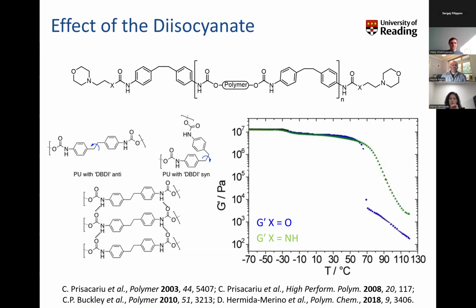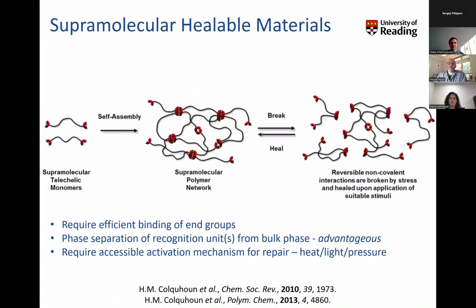We've also varied the diisocyanate, and this was a collaboration with Cristina Prisacariu's group from Romania, where her group had been working with a diisocyanate. Instead of a methylene bridge between the two phenyl rings, there was an ethylene bridge, and that allowed for flexibility of that group to enable more efficient hydrogen bonding. And that's mapped out directly in terms of how these materials assemble and their mechanical properties, where we have far stiffer materials, with an order of magnitude increase in the storage modulus in comparison to the previous systems that I showed you.